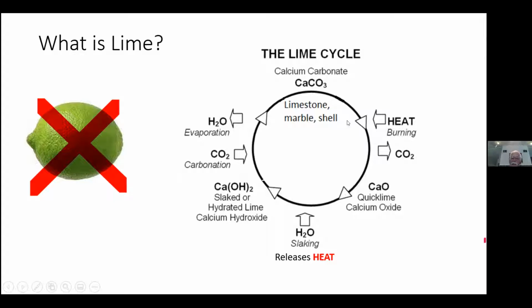The heating part uses up a larger quantity of heat, but then when you slake it and combine it back with the water, it releases heat, almost 90% of the heat that you put in, the, quote, burning of it, gets released back. So it's an endothermic reaction to heat it up to burn the lime, and an exothermic reaction releasing heat when it gets slaked. The slaked lime then is typically used to create a lime putty.